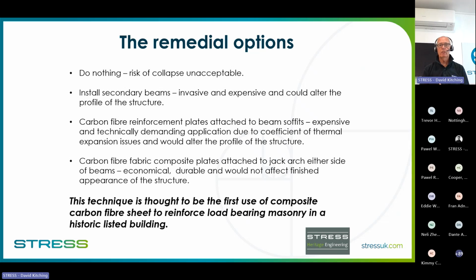You could actually install a set of secondary beams. So instead, take the props out, put something in just a little nicer than props, but pretty invasive and pretty unacceptable on a grade 1 gold star listed structure. But you could use carbon fibre. Now, for those of you who have never seen carbon fibre, that is a piece of carbon fibre plate, 100 mm wide, 1.4 mm thick, stiff as anything. Absolutely amazing stuff, and we use that for strengthening mostly RC, reinforced concrete slabs and beams, but you can use it with steel. So we thought, oh, that'd be quite a neat way, no weight or virtually no weight added.